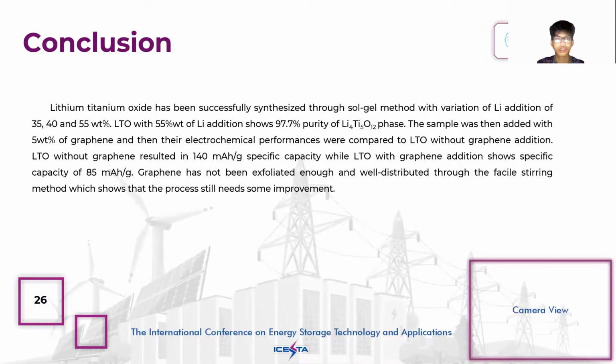Next, the conclusion. Lithium titanium oxide has been successfully synthesized through the sol-gel method with variation of lithium addition of 35, 40, and 55 weight%. LTO with 55 weight% of addition shows 97.7% purity of LTO phase.